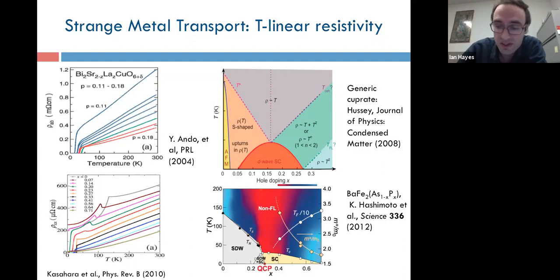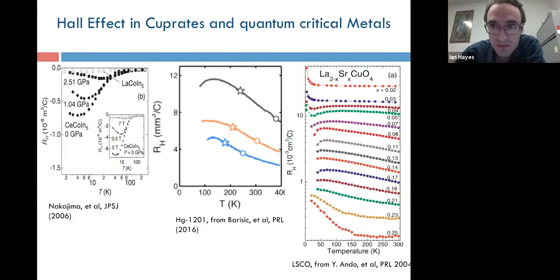So the T-linear resistivity is a famous piece of this, but there's also behavior in the Hall coefficient that is common to all these systems. So most cuprates show a strong temperature dependence, usually an enhancement, but sometimes it's a change in sign of the Hall coefficient that is strongest near optimal doping.